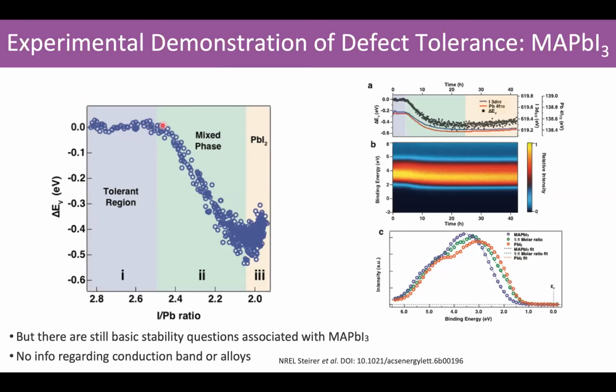Now, it turns out one thing that we aren't looking at here is the conduction band. This is really just the valence band. And it turns out a lot of the defects that we create here are theorized to be in that conduction band right at the band edge. So we're probably making the scattering within that material worse, but we really aren't creating deep levels, and we really aren't changing the electronic gap until we get to a really, really high defect density.